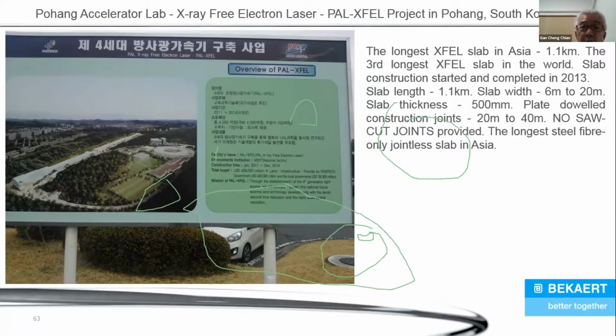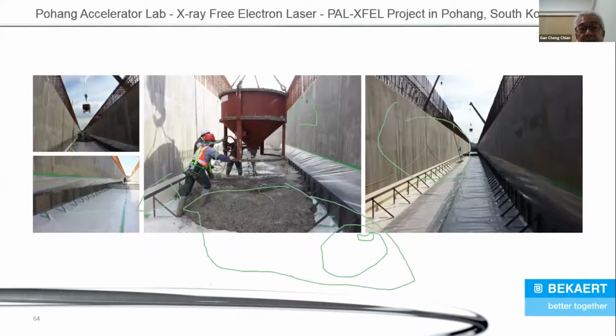And believe it or not, in 2019, the owner of this facility, which is the Korean government, confirmed to the contractor that after 2013 to 2019, after 6 years of usage, the slabs still have no cracks. This is a confirmation that fiber concrete can work to prevent cracks. And this is how it was casted. It was casted with a bucket and they just pour directly onto the narrow slab, and it was done without any saw cuts at all.